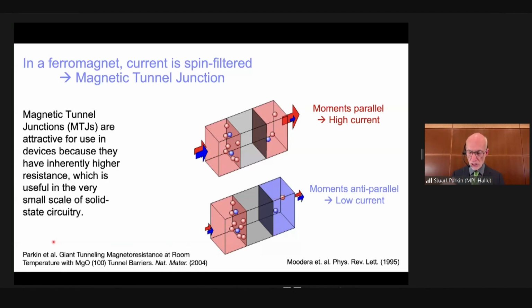So the interfacial characteristic of the spin-dependent scattering was incredibly important. Now, the technology, the spin valve sensing technology based on spin-dependent scattering, evolved after 10 years to essentially the same structures, the same spin valves, but the physics evolved from spin-dependent scattering to spin-dependent tunneling. Now, spin-dependent tunneling was a concept known about from the 1980s.